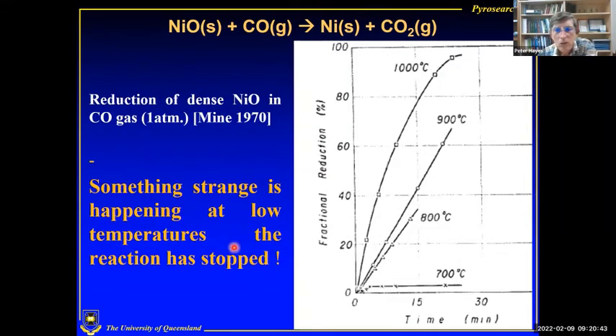What about CO gas? Well, something happening here. As we increase the temperature, the rate goes up, but we find at low temperature, at 700 degrees centigrade, the thing's actually not going at all. Basically, it stopped. So we expect a continuum. Why isn't there a continuum here? Why isn't it slower as we go down? Well, it is slower, but not this. We don't want it to be that slow.